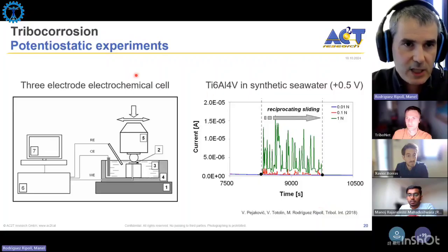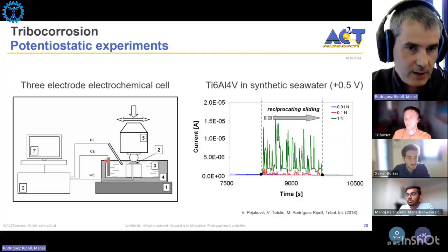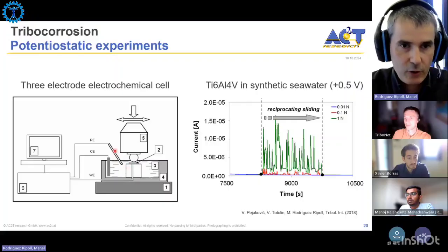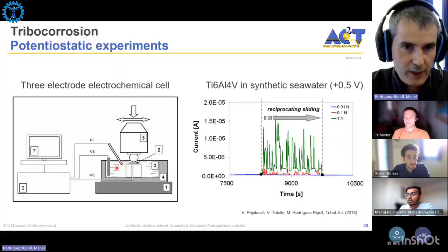So with potentiostatic experiments, we are forced to have 3 electrodes. We need to have the material that is investigated, which is the working electrode. We have a counter electrode that is typically a noble metal, platinum or graphite, and the reference electrode, a stable material not reacting with the media with a well-known potential, to which we refer all other potentials.